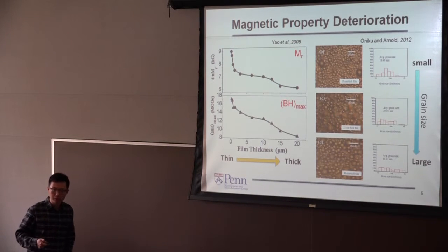So then you say, you just deposit thicker films. What's the problem? It wasn't that easy to scale up. One of the problems you have is this property deterioration. As one of the examples shown over here, you see that the magnetization and the BH max both decrease when the thickness goes thicker. And note that tens to hundreds of microns actually will be really interesting in MEMS devices.